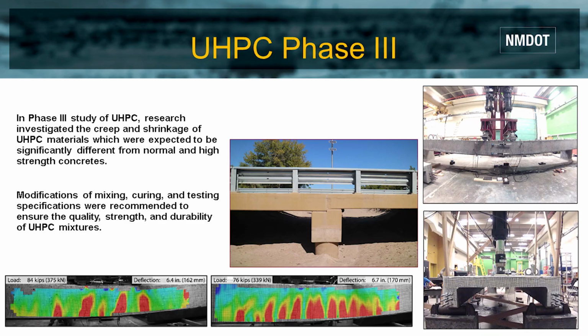In phase 3 of the study, research investigated the creep and shrinkage of UHPC materials, which were expected to be significantly different from normal and high-strength concrete. Modifications of mixing, curing, and testing specifications were recommended to ensure the quality, strength, and durability of UHPC mixtures. Additionally, the design behavior of UHPC girders was investigated through large-scale flexural tests.